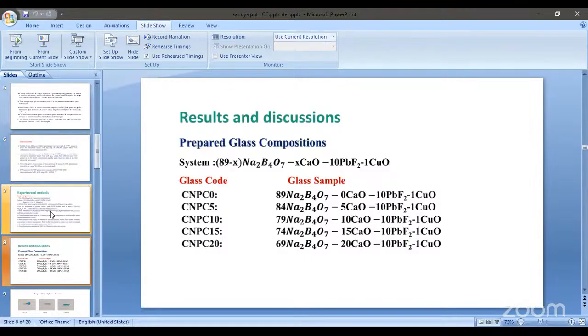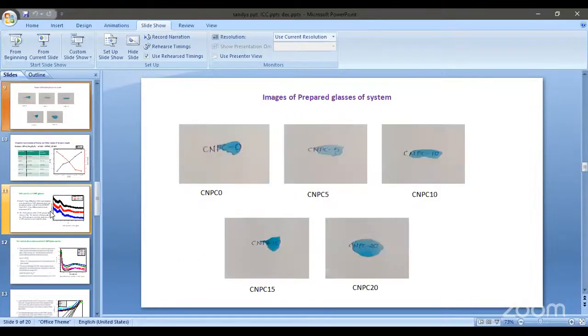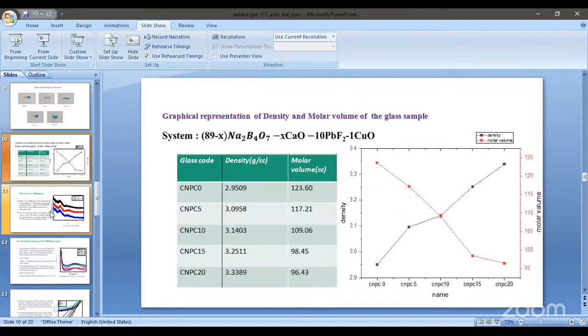Here the prepared glass compositions are like this. This is the glass code, and these are the glass samples, where x equals 0, 5, 10, 15, and 20, and these are the images of the prepared glass systems. This is a graphical representation of the density and molar volume of the glass samples. Here the density increases and the molar volume decreases with increasing mole percentage of calcium oxide.